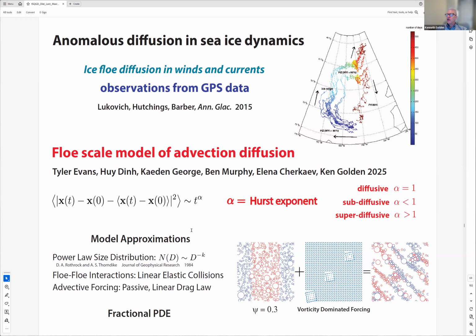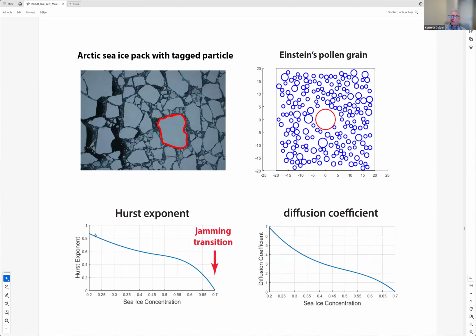And how do the advective contributions, the currents and the winds, affect this? And also there's a jamming transition, which we see. So here's the Hurst exponent. And then also this is, I guess, a jamming transition. When it gets above about 70%, things just kind of jam up and the Hurst exponent goes to 0. And part of my idea was to treat an ice floe like Einstein's pollen grain and do that calculation, basically. And that's been guiding us, basically.